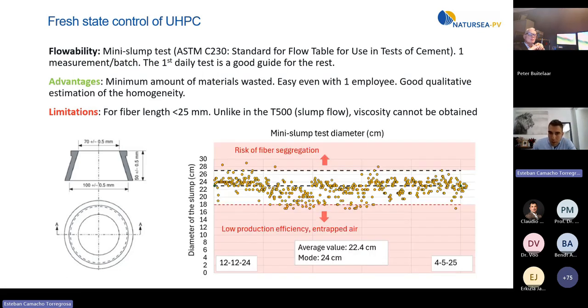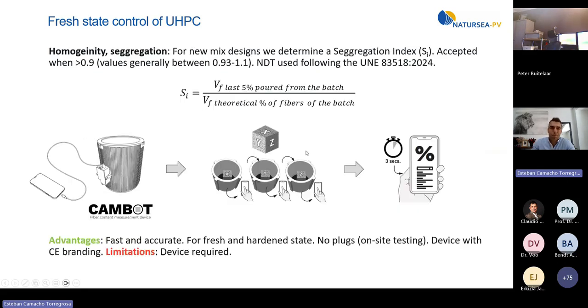This is the result of the diameters of the batches that we have controlled in the last months. As you see, they are always between 18, 19 and 27 centimeters. Below 18, the filling of the elements is too slow. This decreases the competitiveness and the productivity ratio in the company. And you may also have problems of entrapped air, because it's not as self-compacting as it should be. For higher slump diameters, over 27, there is already a certain risk of fiber segregation. So we try to stay within this limit.